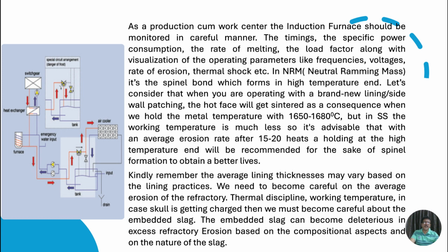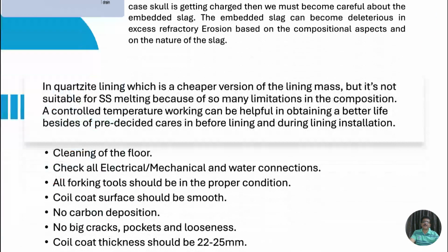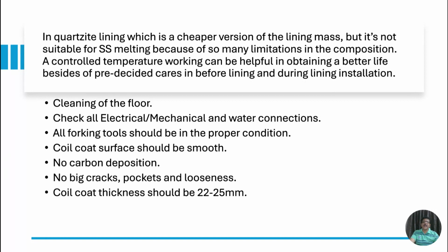Thermal discipline, working temperature: in case skull is getting charged, then we must become careful about the embedded slag. The embedded slag can become deleterious, causing excess refractory erosion, based on the compositional aspects and on the nature of the slag. Quartzite lining is a cheaper version of the lining mass, but it's not suitable for SS melting because of so many limitations in the composition.